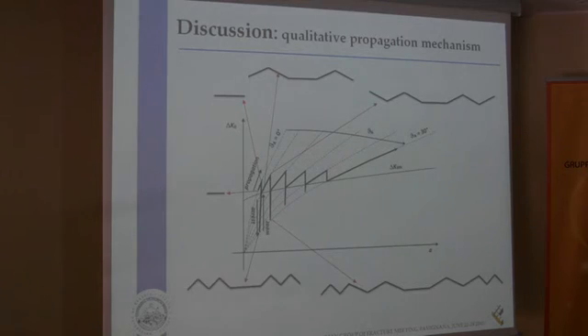But wear is supposed to act also on the arrested crack by smoothing the asperities between the crack surfaces during the contact cycles, thus increasing the stress intensity factor, and if this reaches the propagation threshold again, the crack is further allowed to propagate for a step. But after this step, new rough regions appear at the crack tip, so the stress intensity factor is again decreasing, and so on. So the crack is expected in the first stage to grow by a subsequent stop and go until it becomes large enough to propagate in a continuous way.